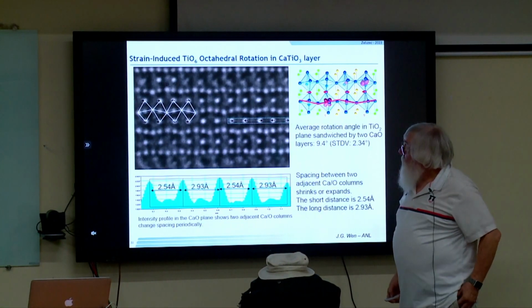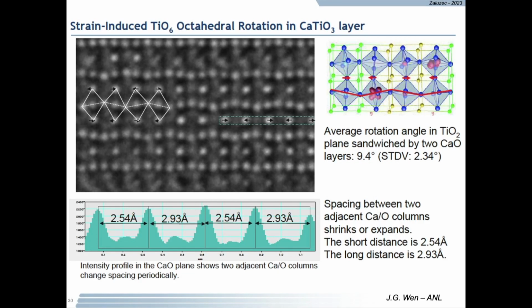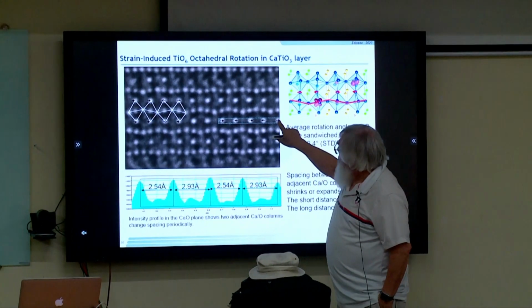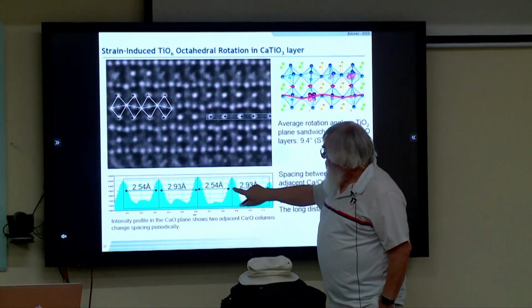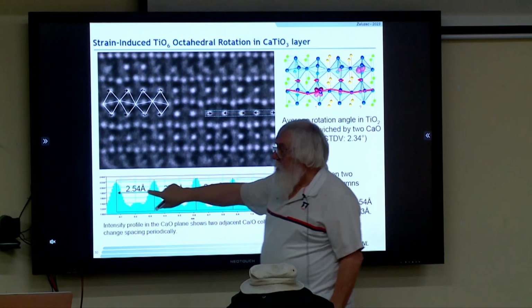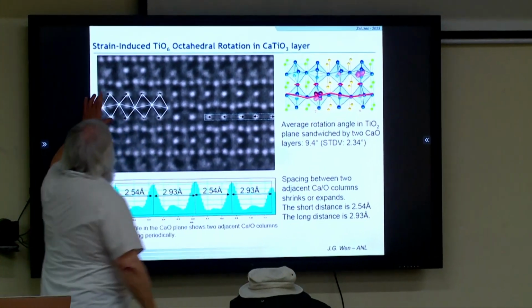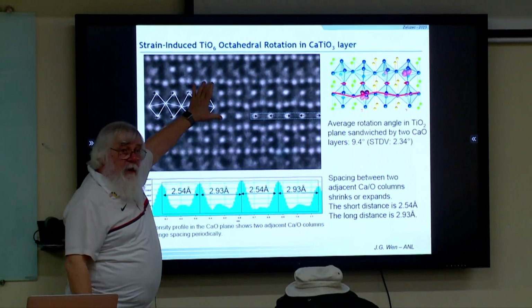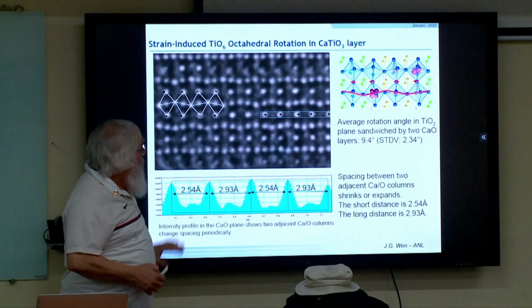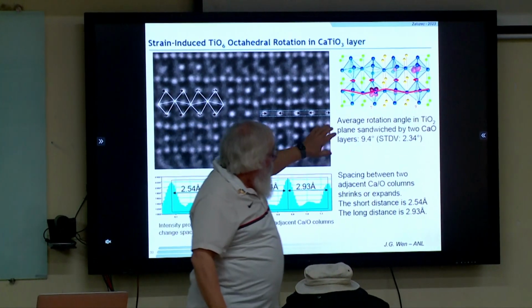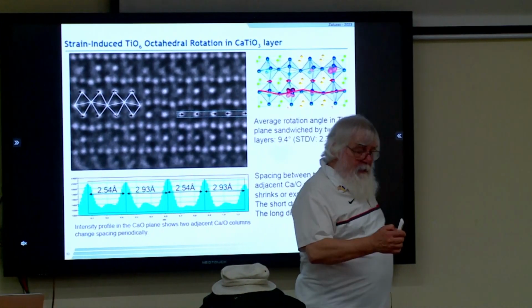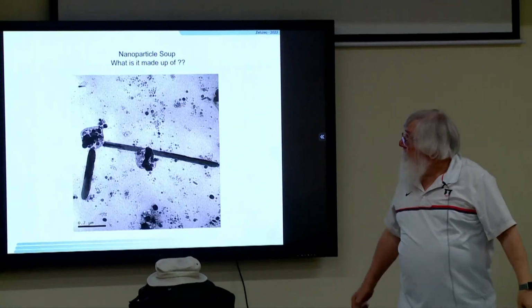We'll look at high resolution imaging. This is a calcium titanate layer, and what we're seeing is atomic resolution imaging. There's a scale bar here when we're looking at the spacing between individual atoms. And we see changes in that spacing. We also see rotations of the octahedra in there. All of that has to do with how the material is grown and what its properties are.